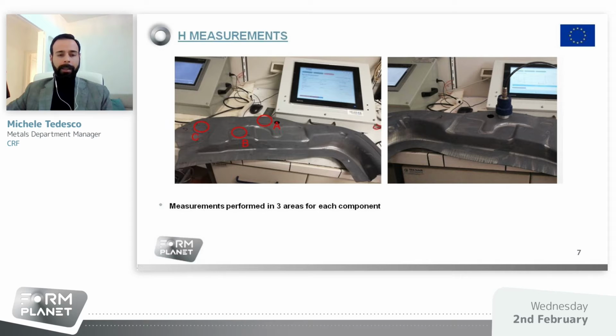After the stamping, we performed the same analysis, so the diffusible hydrogen measurement on the stamped component in different areas of each component. Because changing the areas, also the concentration could change, because the cooling under the die is not uniform and depends on the shape of the component that we are stamping.